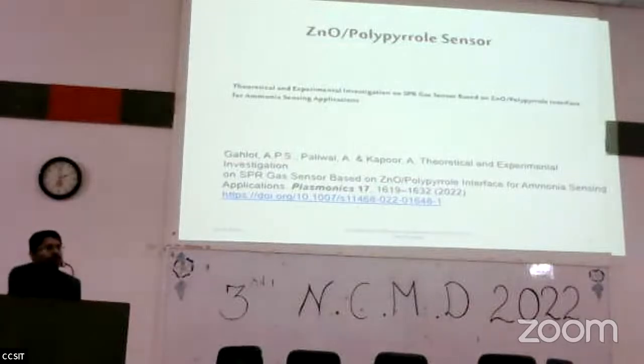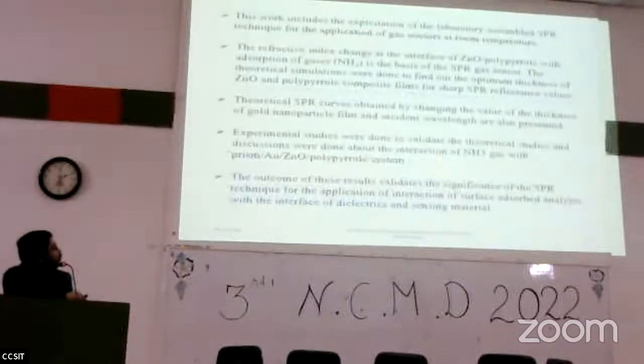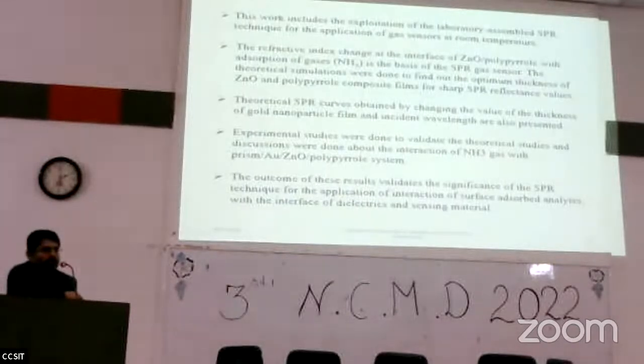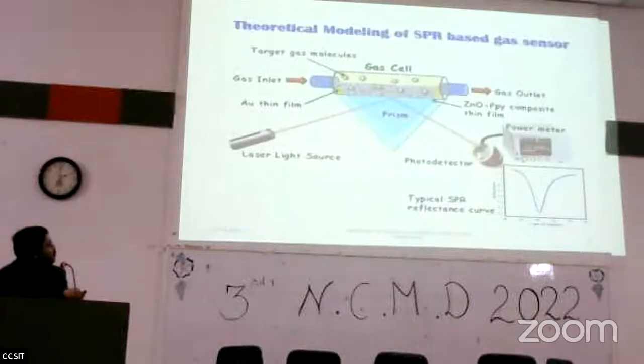So now we come to our first work. It was published in Plasmonics this year. As I told you, this is based on the surface plasmon resonance principle. First, we optimize theoretically the thickness of the metal film, gold film, then the ZnO film and the polypyrrole film, and then with these optimized values we obtain experimental results with varying concentrations of ammonia gas. This is our model. Here we have the chamber attached to the prism.